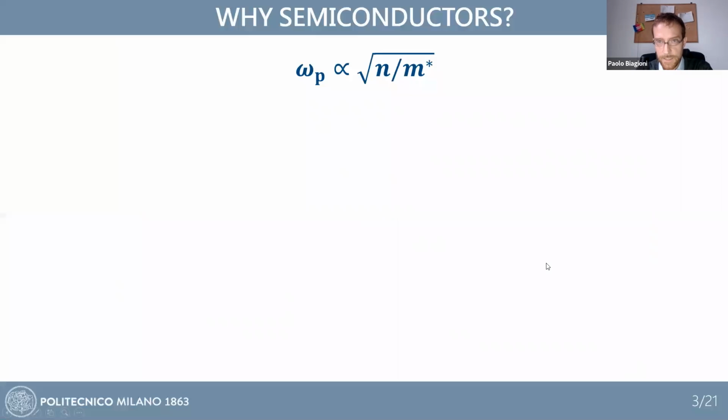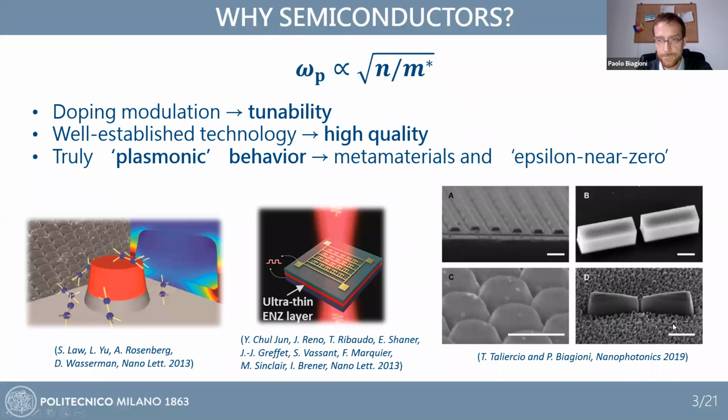So we fabricated antennas, yes, indeed, after laser annealing. Actually, one of the examples that I showed you in the beginning, this bow tie antenna here, is a germanium antenna fabricated with very heavily doped germanium films. This is fabricated by focused ion beam milling rather than electron beam lithography, and was studied with infrared AFM nanoscopy. And indeed, with laser annealed materials, we were able to reach much higher plasma frequencies, and we were able to demonstrate that the antennas could resonate at such higher frequencies.